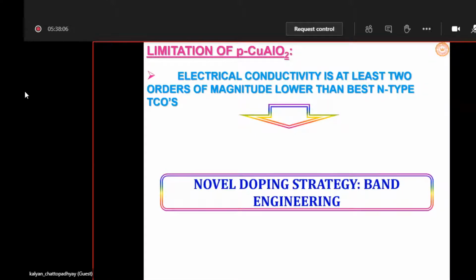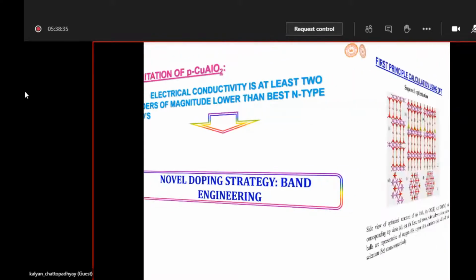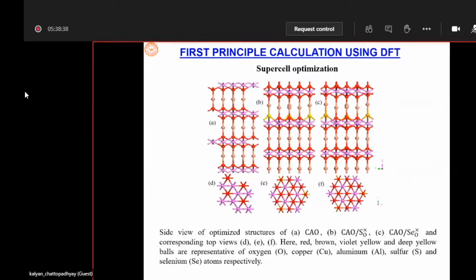Based on this idea, we thought that we will try to dope at the anionic site with some less electronegative element. For example, you know that the chalcogens, sulfur, selenium, tellurium, are less electronegative than oxygen, and we try to replace some of the oxygen, that is, doping at the anionic site, in such a system. But as you know, doping at the anionic site is not so straightforward. So to check whether our thinking is right, we have performed extensive density functional theory based calculations.